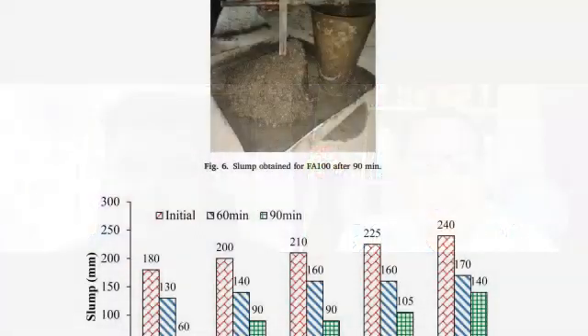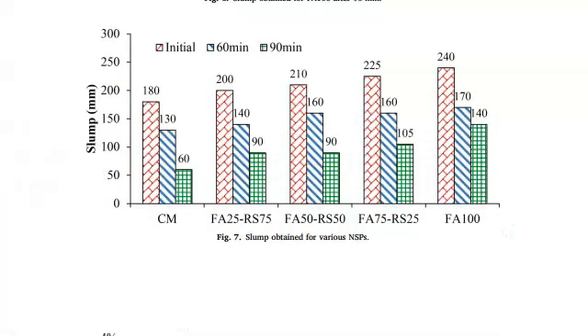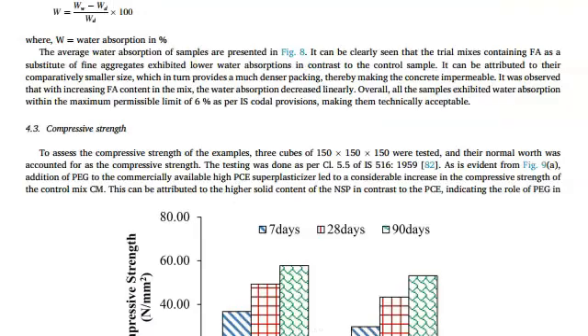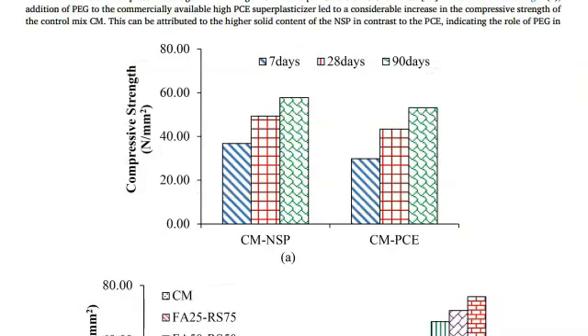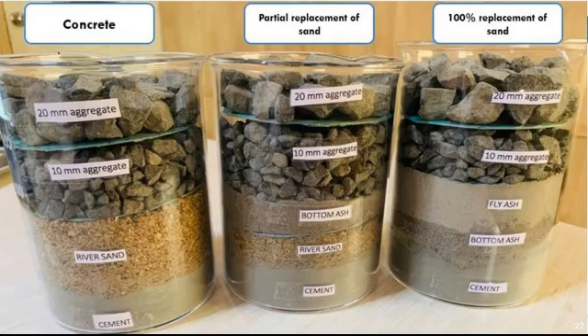On the other hand, the huge quantities of waste that were being generated in India were still being dumped in landfills and so on. So that needed to be addressed, because landfilling is not a permanent solution, as it leads to various environmental hazards. So I tried initial lab trials by incorporating the fly ash and bottom ash in a traditional concrete mix as a replacement of natural river sand. But as observed in the past studies, when I carried out the replacement for greater than 50%, that means 50% sand was replaced by ash, I observed a stagnating decrease in the overall strength, which motivated me towards analyzing the